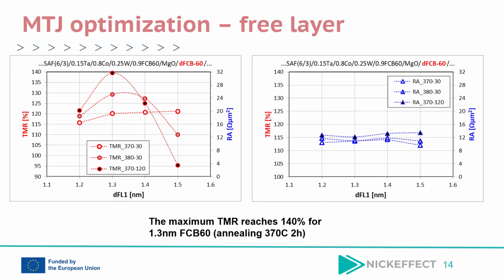The highest TMR value, reaching approximately 140%, was obtained for FCB thickness of 1.3 nanometer after annealing at 370 degrees C for 2 hours. The RA product shows only minor variation with the FCB thickness, confirming stable tunnel barrier quality during the optimization process. These results demonstrate the strong influence of the free layer thickness and annealing conditions on the MTJ transport properties and confirm the importance of precise free layer engineering for achieving high-performance MRAM structures.